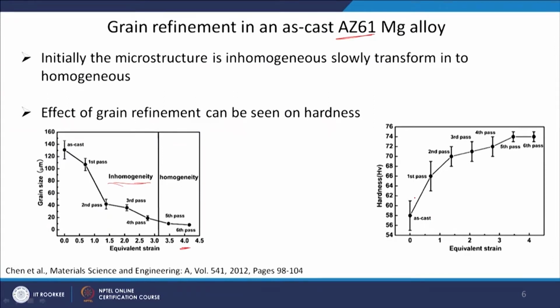Of course, it will have an effect on the mechanical properties of the material. So, as your passes are increasing and the material is becoming homogeneous and getting refined also, by 5th, 6th pass your hardness is increased from 58 HV to around 74 HV here, again as a function of equivalent strain.